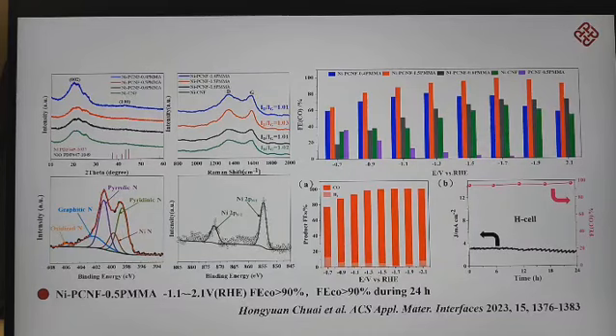PMMA addition, Ni-PCNF from PMMA, maintains a CO Faradaic efficiency of more than 90% within the potential range of -1.1 to -2.1 volts vs. RHE, and showed good CO Faradaic efficiency during the 24-hour test.